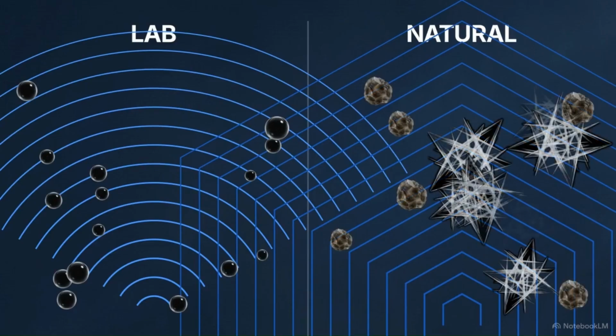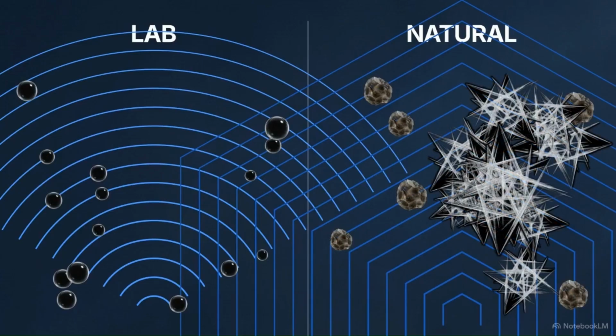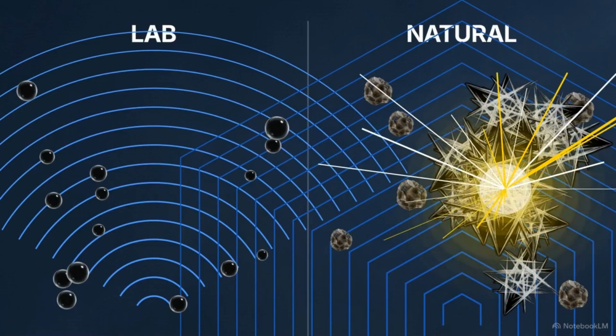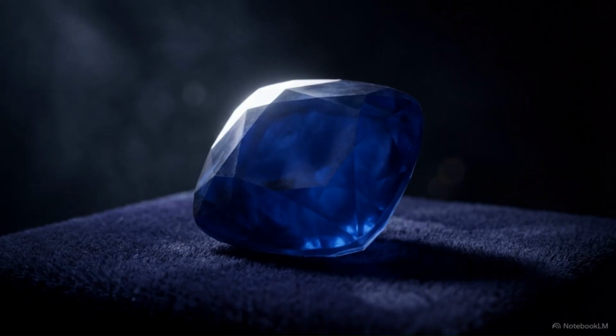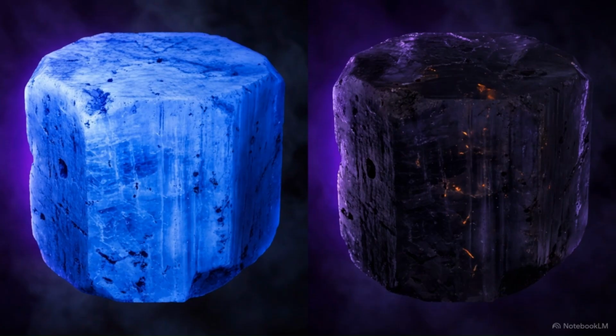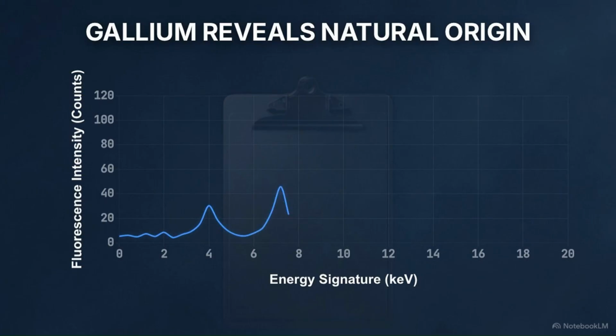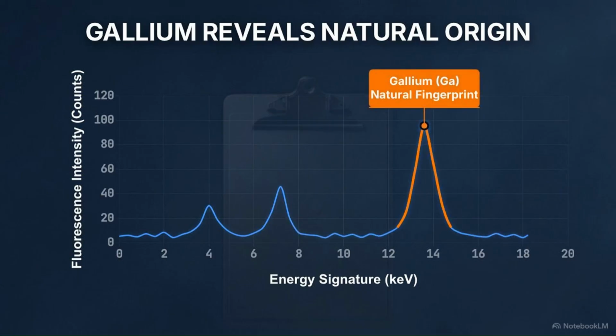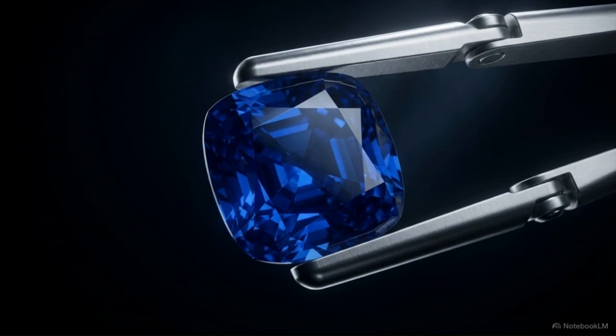At those extreme temperatures, the rutile silk actually dissolves back into the corundum lattice, which clears up the cloudiness and vastly improves the clarity. And furthermore, if you carefully control the oxygen levels in the heating furnace, you can force the iron and titanium atoms within the lattice to interact more efficiently. Dramatically intensifying that blue color. Exactly. Which perfectly explains why an unheated natural sapphire, one that emerged from the dirt with perfect clarity and vivid color without any human baking, commands such an insane price. It's a statistical anomaly. It truly is.